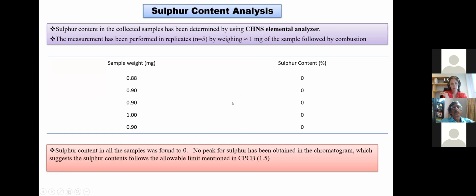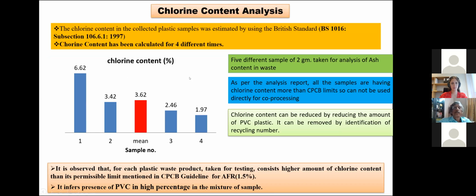So the next one is the sulfur content, which we have tested through the CHNS analyzer. 5 different samples of approximately 1 milligram weight have been tested through the analyzer. The sulfur content for all samples was found to be 0, as no sulfur peak was found. So that also suggests that the sample can be used as an AFR.